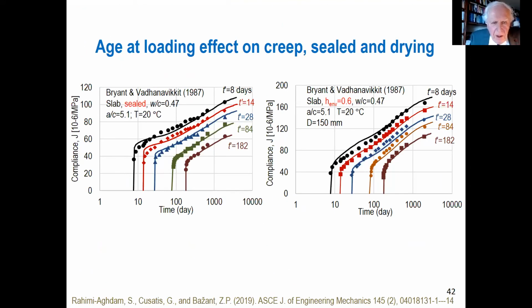Okay. We can also fit the data for different ages of loading. Concrete, so this is hydration effect together with micro-prestress. If you take only hydration volume, which was thought before, hydration goes on, but volume does not increase much after the first year. And to explain why there is an age effect after that, you need the relaxation of micro-prestress. As it relaxes, the structure becomes more compact, less disturbed, it creeps less. And that goes for decades, for years.